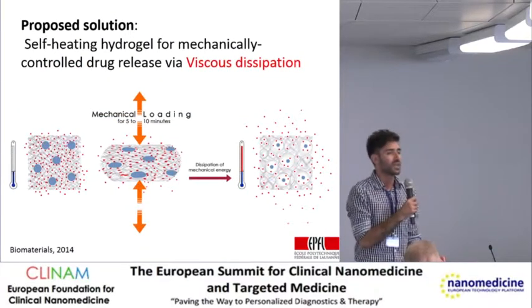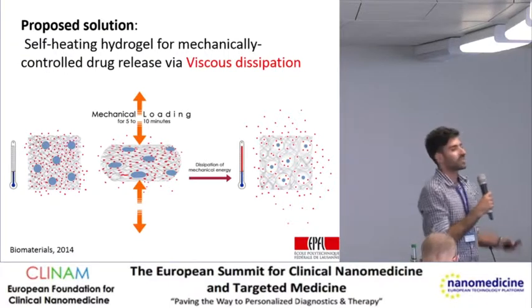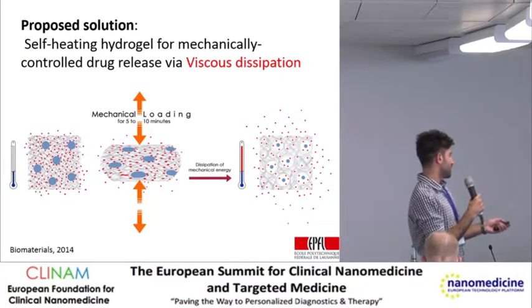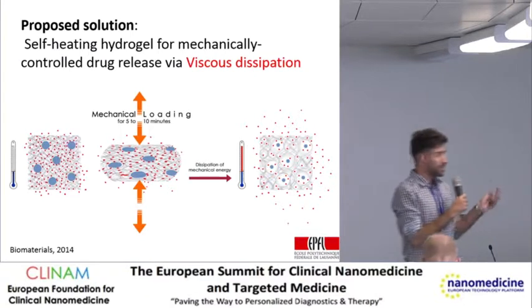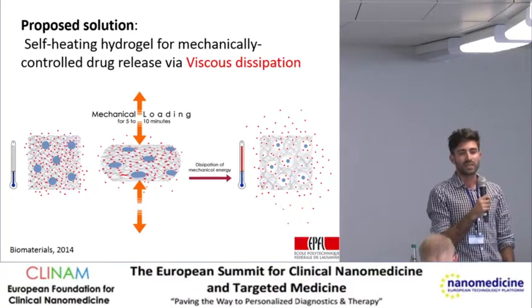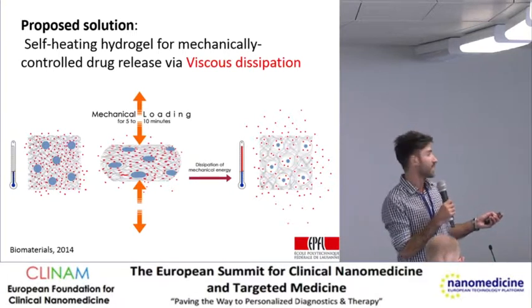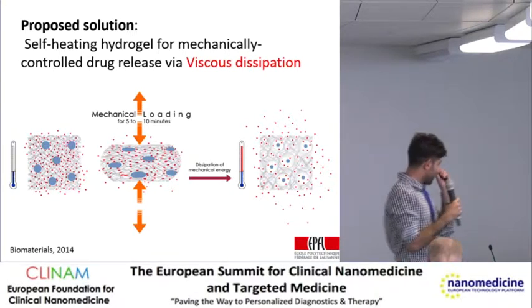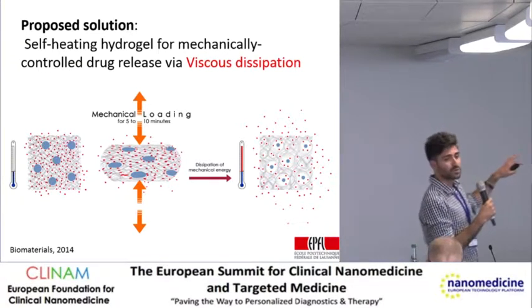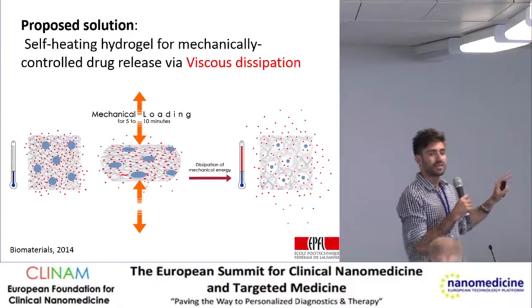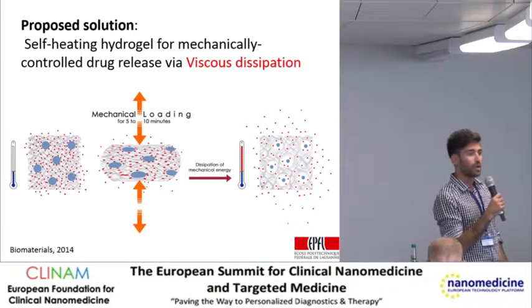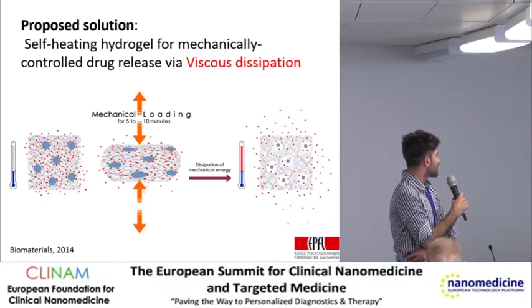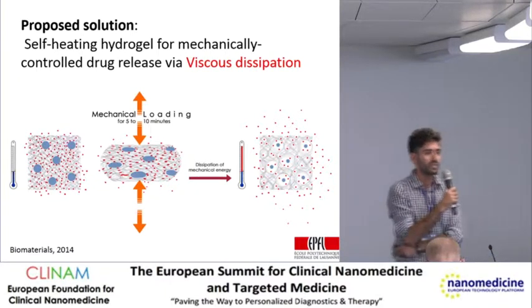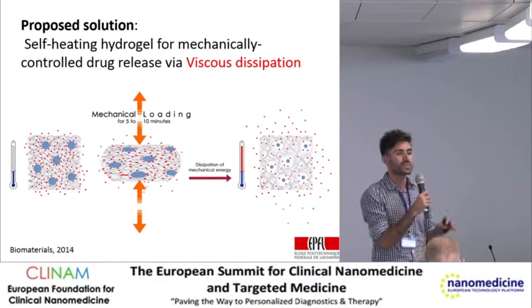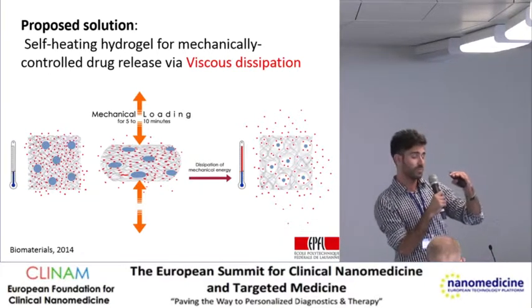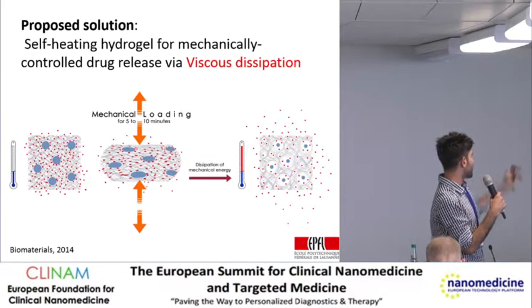What we propose here is to introduce a new variable. It's not new, but for drug delivery systems, it is viscous dissipation. With this parameter, we can control the release of drug with mechanical load and, as I said, provide such a delay. The system that we propose consists of two components: a hydrogel system, which is very viscoelastic with low permeability, and inside this hydrogel, some thermosensitive nanoparticles that are designed to shrink when the temperature reaches their critical temperature. So imagine that you apply load on this system.